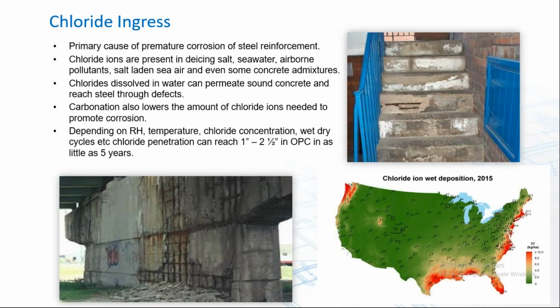Chloride ingress. Two-thirds of our population actually live in coastal states. One-third of our population actually live in coastal counties. So, they're a very aggressive environment with the salt-laden sea air. And chloride ingress is really the primary cause of corrosion of steel reinforcement. Chloride ions are also present in the de-icing salts we use on our roads during the winter time. Airborne pollutants, as I mentioned, salt-laden sea air, and even some concrete admixtures also contain chloride ions. These dissolved in water permeate sound concrete and reach steel through defects.